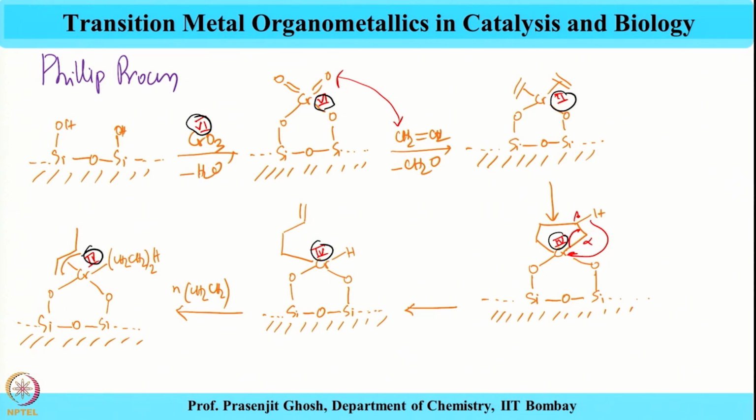So, this is a heterogeneous process in which this high density polyolefin can be obtained at very low moderate pressure, about 10 to 30 bar, and give well behaved high density polyethylene. This chemistry is being done by chromium, which is also early transition metal.